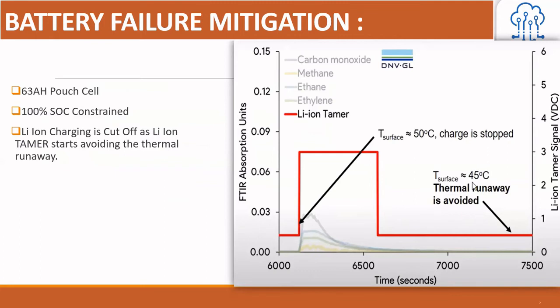So there are different gases that we have, and once this gas detection is sensed, the cutoff could happen. Like, the charging was done at 50 degrees centigrade for this 63 Ah pouch cell. So it is having emissions of carbon monoxide, methane, ethane, and ethylene. These are the different volumes of gases that were present and got emitted during the charging, meaning the abuse happened during the charging, and at different times these amounts of gases are getting emitted. So once this is sensed at a level beyond a particular threshold,